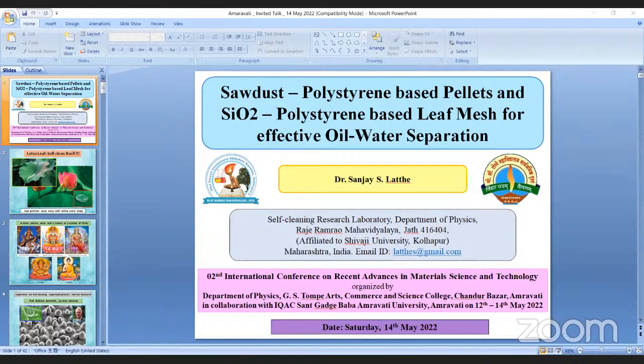Next. So, conclusion: as I said, with 100 milligram per milliliter of polystyrene and 100 milligram of sawdust, if we prepare the nanocomposite of this, we can get oil water separation membranes using sawdust. It is a 3 for 1, and it can be industrially used. The commercialization can be possible.